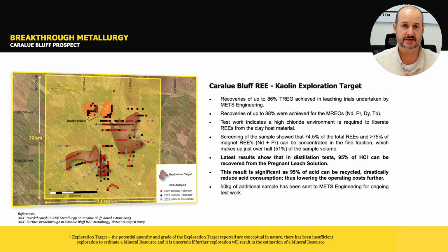So our metallurgical test work has been going on probably for the past 12 months now. And like I mentioned before, we've had a number of breakthroughs. The first of those is that we've been able to achieve 86% recovery of the total rare earths and about 88% of the magnet rare earths, which are neodymium, praseodymium, dysprosium, and terbium.